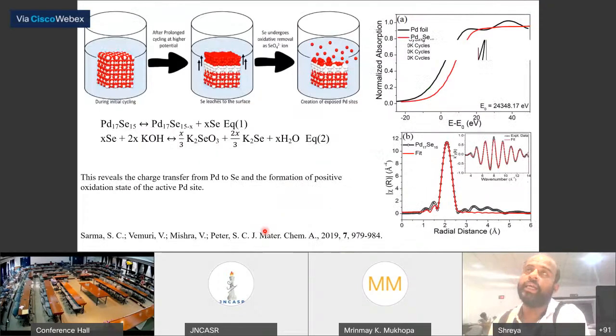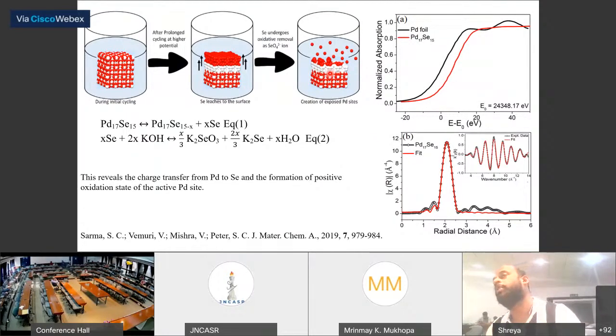So we propose the mechanism, what is happening in the palladium 17 Se15 structure. Upon treatment in the harsh condition, selenium slowly etches out of the system, as you see in this equation, and then selenium is leached out of that system and it also forms a protective layer at the surface of the palladium.